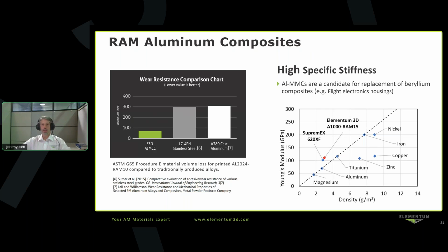I mentioned a little bit that you can control specific stiffness or modulus with this process as well. Here's an example of our Elementum 3D 1000 series aluminum RAM 15 composite. It's shown compared to a bunch of elemental metals: magnesium, aluminum, titanium, zinc, copper, iron, nickel. If you followed that line upwards, you would see others, molybdenum, tungsten, and so on, also fall either on or below that line. Almost all elemental metals fall on or below that line for modulus versus density.